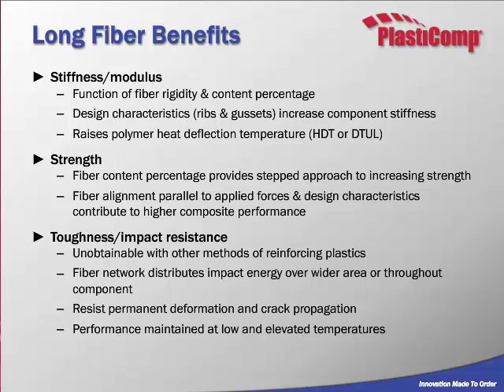That's one advantage that long fiber has: because of our processing methods, we're able to go into reinforcement levels that are higher than what you could typically achieve with a short glass product or a short fiber product. So that gives us the ability to increase stiffness even further. When you look at unreinforced materials, adding any type of reinforcement, whether short or long, is going to raise your heat deflection temperature. So both can do the same in that regard. With strength, that is also more a function of content. However, fiber length will play a part there, and we have a slide coming up that's going to demonstrate that.